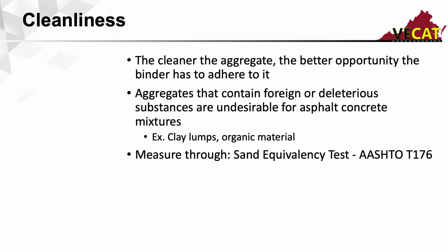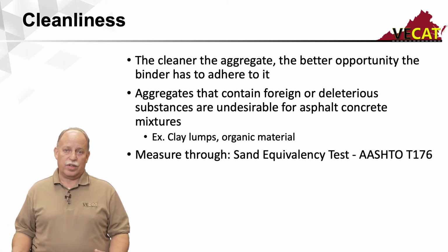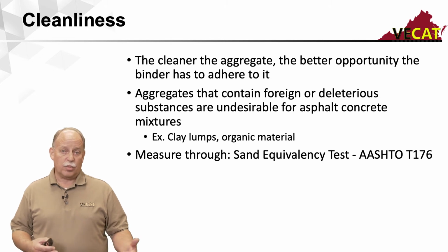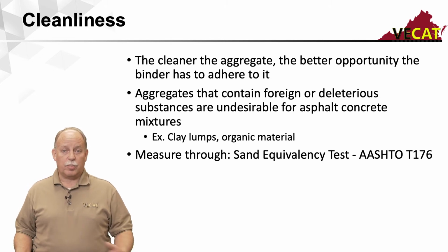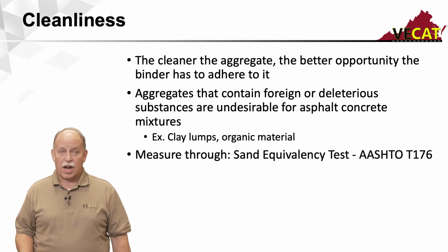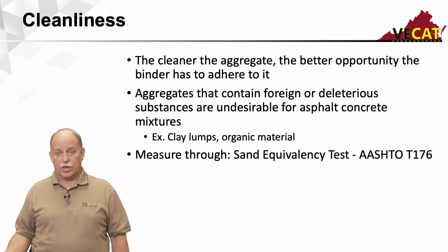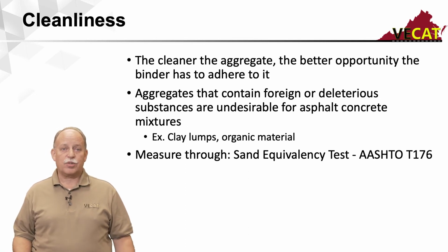Let's talk about cleanliness. The cleaner the aggregate, the better opportunity for the binder to adhere to it. If you think about it, if you have paint and you're painting a room, if that wall is dirty, the paint wants to stick to the dirt, not to the wall. Same thing with these aggregates. If the aggregate is dirty, the binder is not going to want to stick to that aggregate very well. Aggregates that contain foreign or deleterious substances are undesirable in our concrete mixtures. We don't want things such as clay lumps or organic material to be included in our mixes. And that's measured through something called the sand equivalency test. That's AASHTO T176.